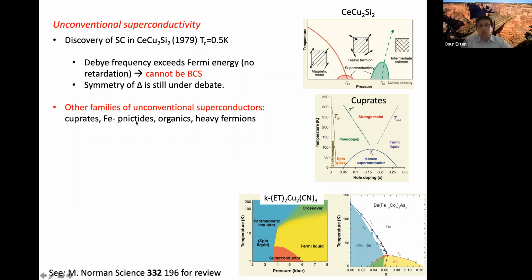So what really kicked off the field of unconventional superconductivity is the discovery of cuprates, or copper oxide superconductors, because these have TCs on the order of 140 Kelvin. That's much higher, at least 5 times more than any other BCS-like superconductor. And if you can double that, then you completely revolutionize technology. You could have room temperature superconductors, or close to room temperature. So that was really a driving force to understand them.